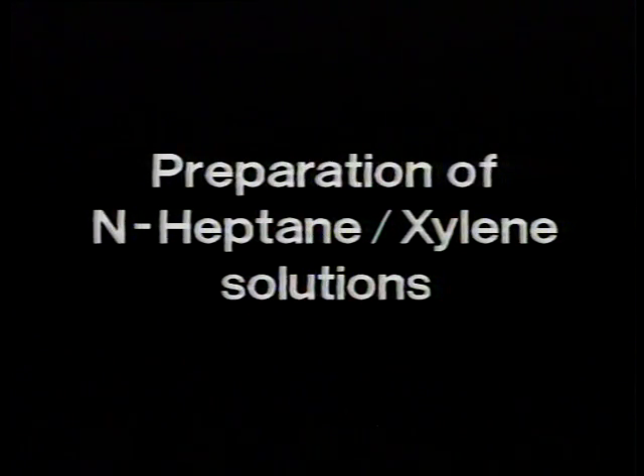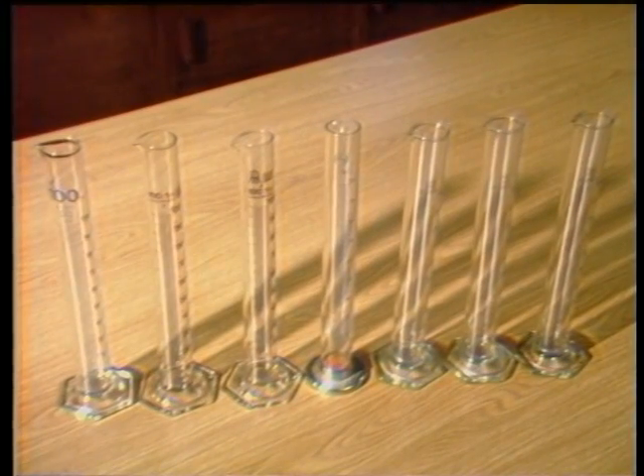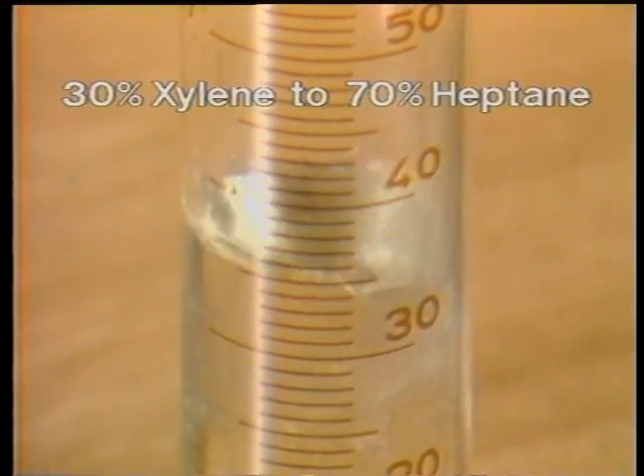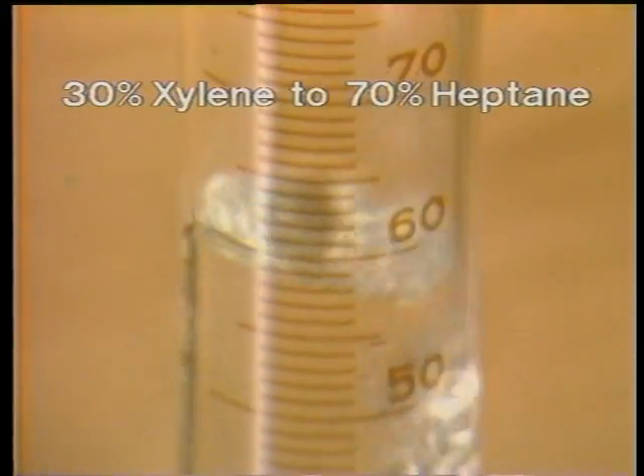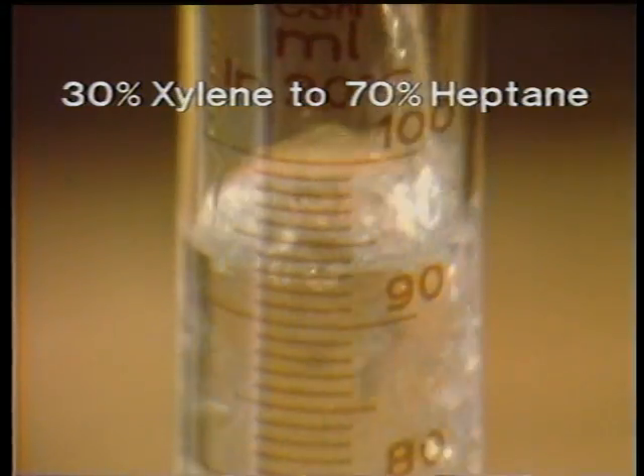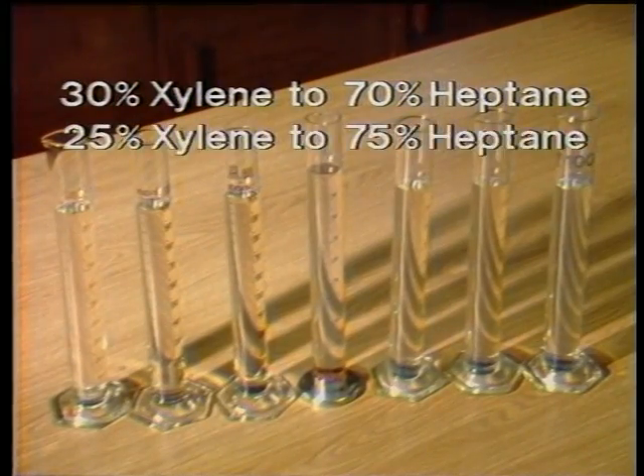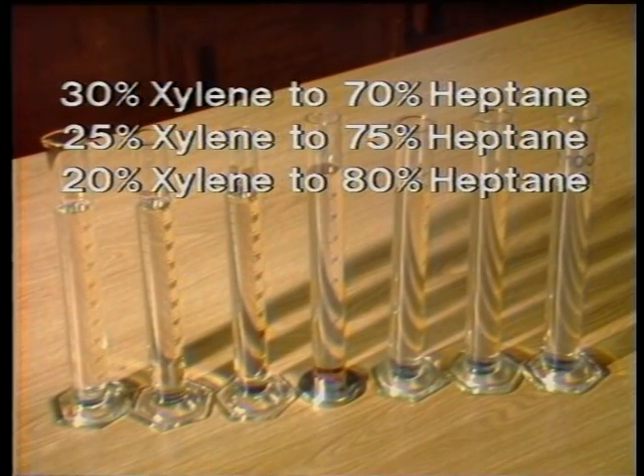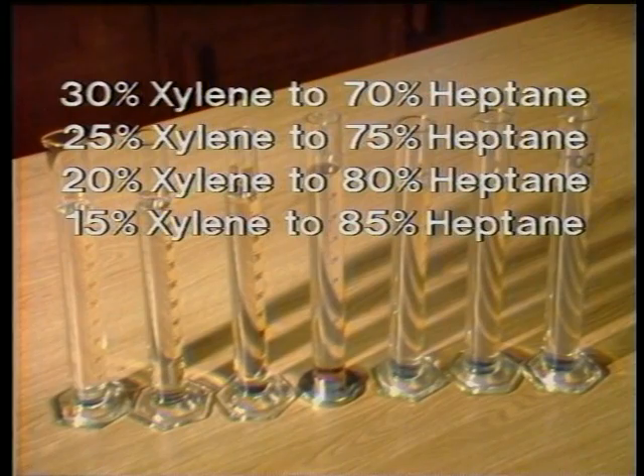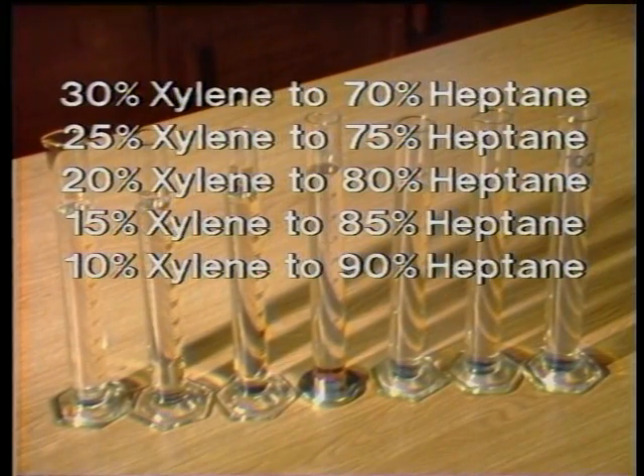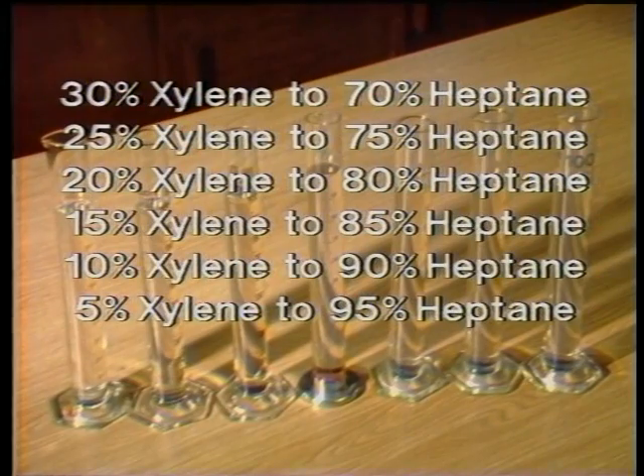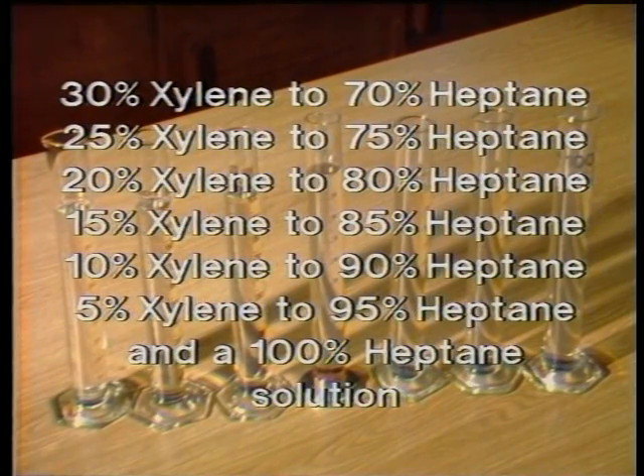Preparation of heptane-xylene solutions. Using your 7 100 milliliter measuring cylinders, make up solutions of 30% xylene to 70% heptane, 25% xylene to 75% heptane, 20% xylene to 80% heptane, 15% xylene to 85% heptane, 10% xylene to 90% heptane, 5% xylene to 95% heptane, and a 100% heptane solution.